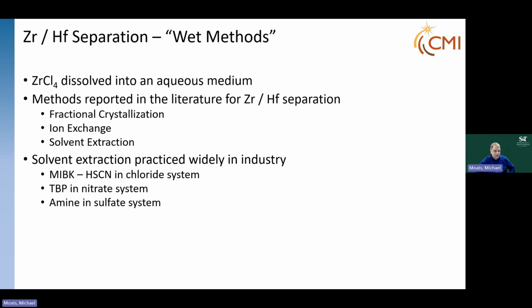So we've got to zirconium hafnium separation. We have a zirconium hafnium chloride. It's a solid coming out of the condensers. That's dissolved in an aqueous media. That aqueous media depends on the type of solvent extraction or the type of separation used. Historically, fractional crystallization, so preferential precipitation, can be done. It's very intensive from a number of stages. People have been looking at ion exchange more recently, but most of the plants in the world use solvent extraction.